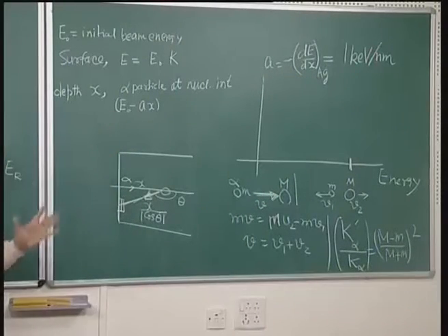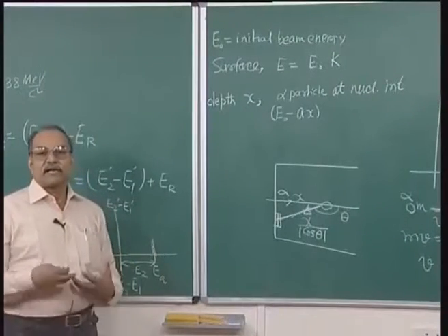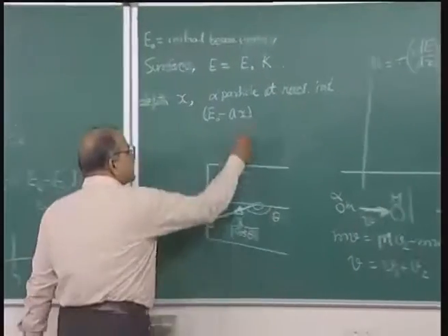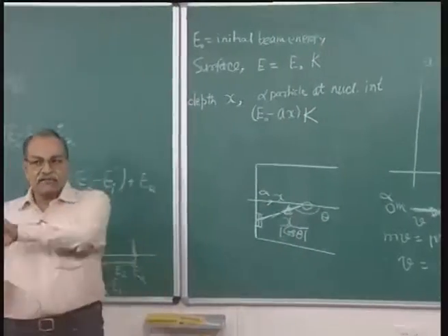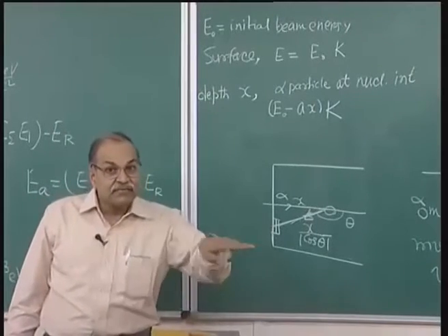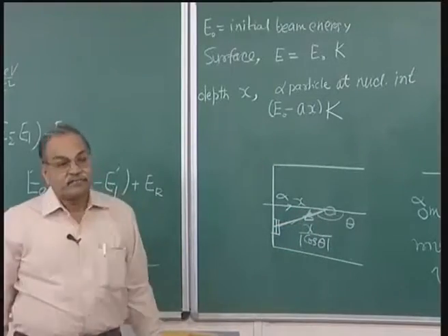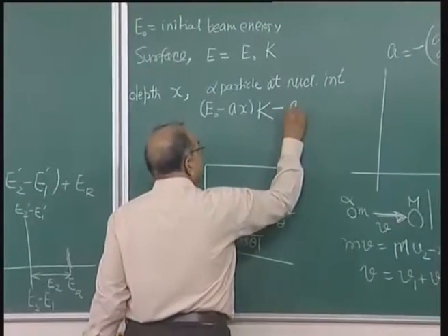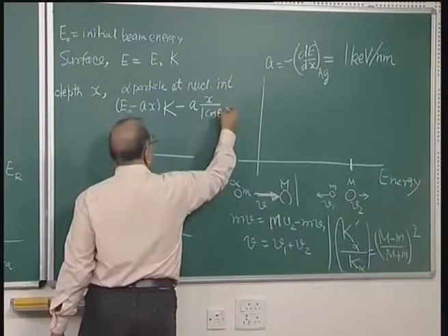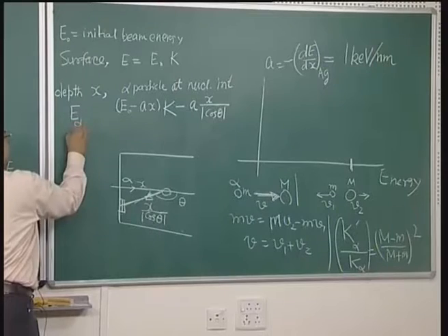So, this is the energy with which this alpha particle collides or interacts with that nucleus, then multiplied by that kinematical factor k. So, when the alpha particle back scatters, it has this much energy, and then it comes through that solid, comes out of the solid and then reaches the detector. During that process, it has lost this much energy. So, this is the energy which is detected.